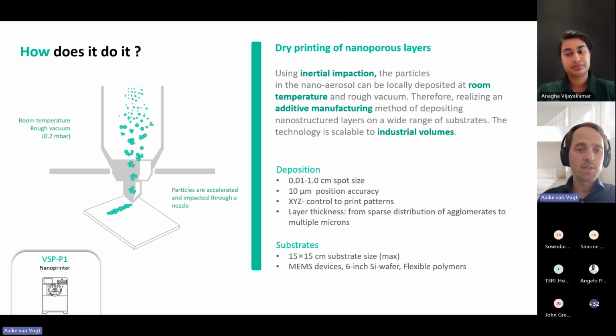So basically, you just have a printing nozzle that you can control in XYZ to print any pattern that you need. The spot size that you can print is, let's say, 100 microns or thicker, but can be tweaked to your specific desires. The printing stage is at the moment, I would say, 12 by 12 centimeters effective printing. So you can go to relatively big substrates already in this R&D printer.